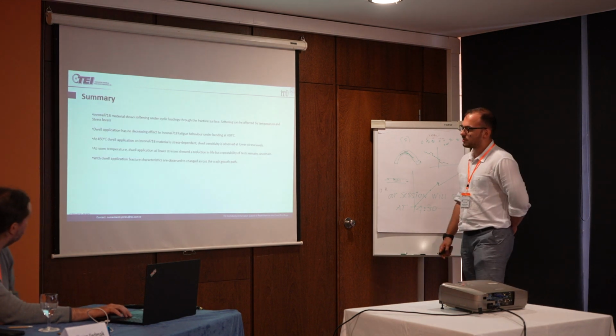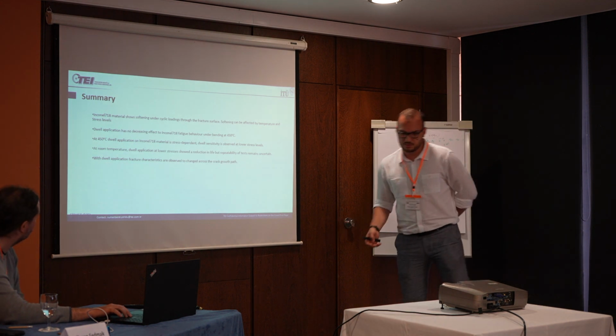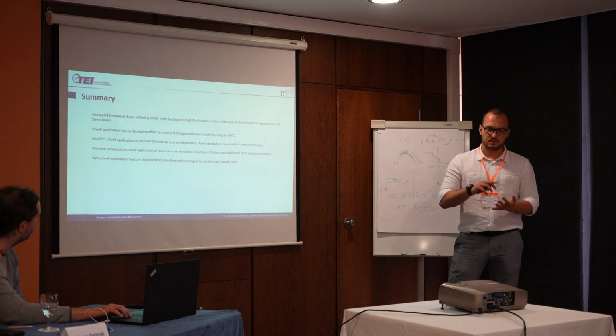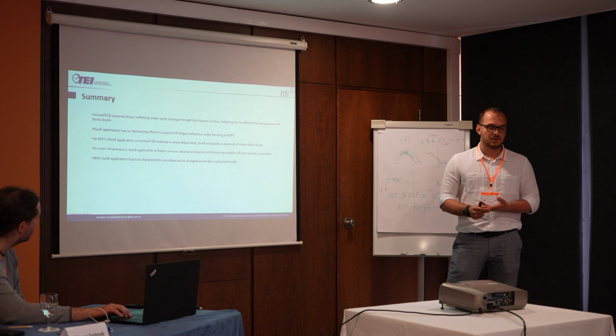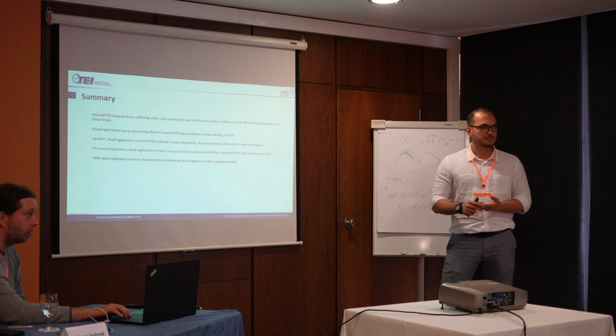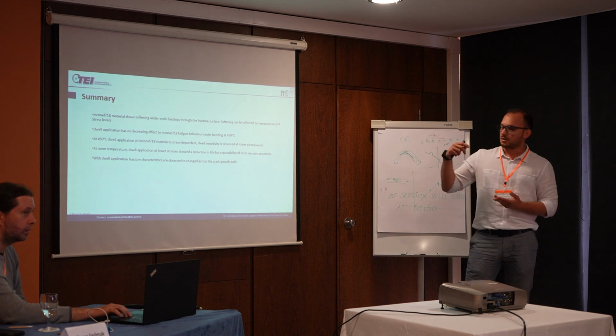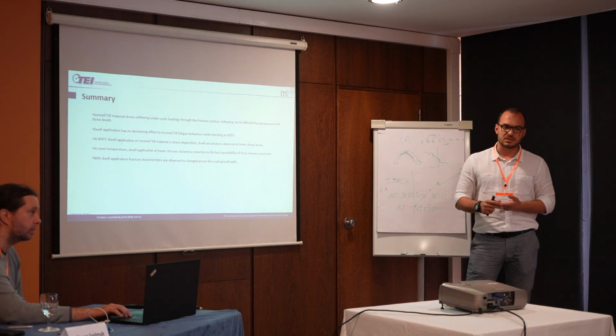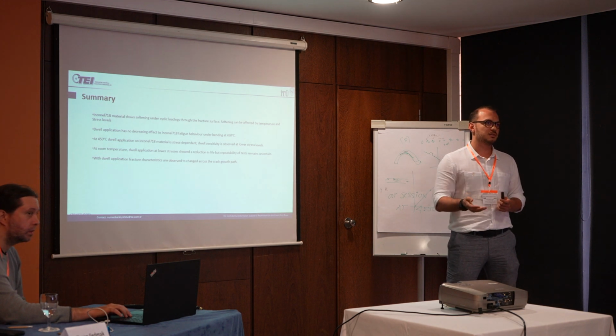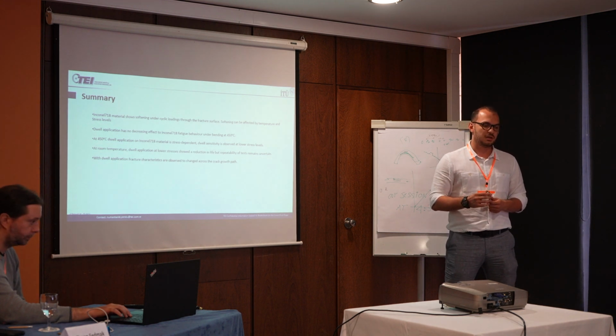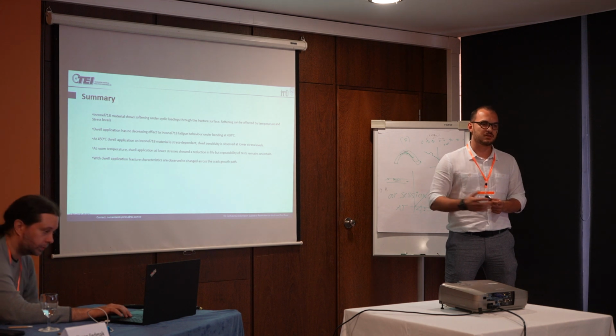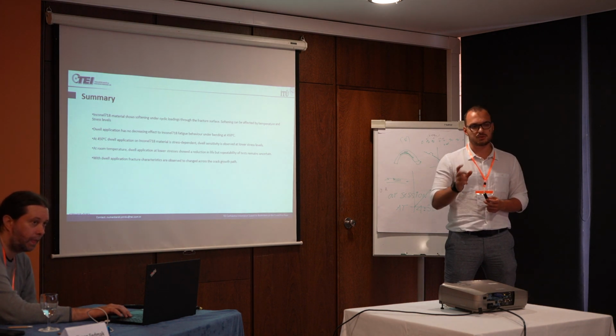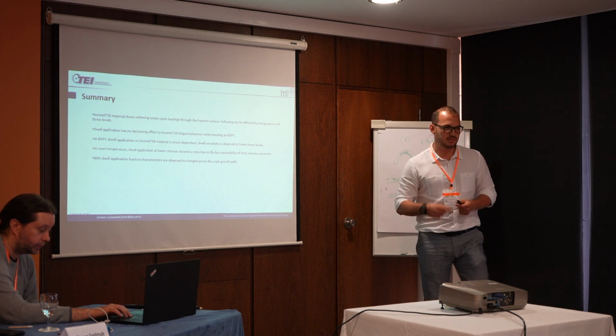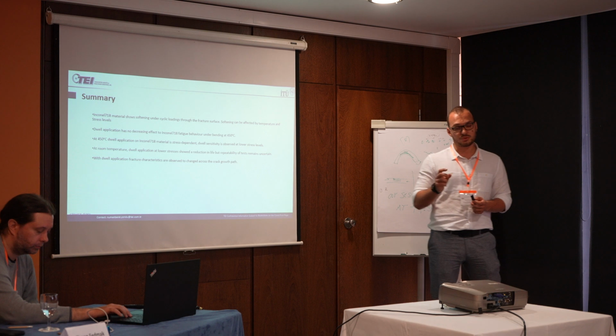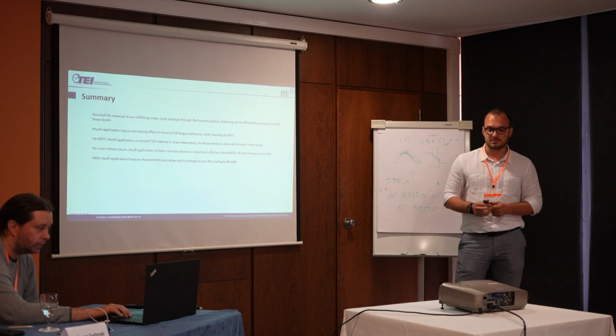We can move on to the last slide. And for summary, we did some high temperature and room temperature rotating bending tests, and after that we applied some dwell during these tests. With that dwell application, we see that the dwell effect is highly dependent on the stress levels. And in terms of thermal effect, I believe there is some effect, but because of the lack of test numbers, I'm not sure of it. There is a little bit of uncertainty, but we can say that